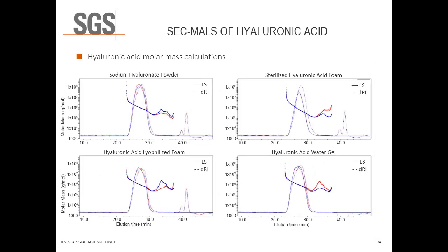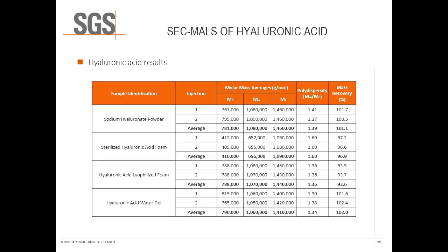When given adequate information, however, very real and useful data is achieved. The results generated by these experiments, which you may notice produce rather broad chromatographic peaks, show that at roughly 1 million grams per mole, these samples were on the low end of what would be expected from hyaluronic acid. Mass recoveries were reasonably close to 100%, considering that there may be differences in moisture content, salt content, and purity between the samples.